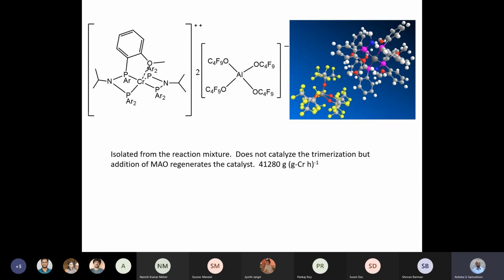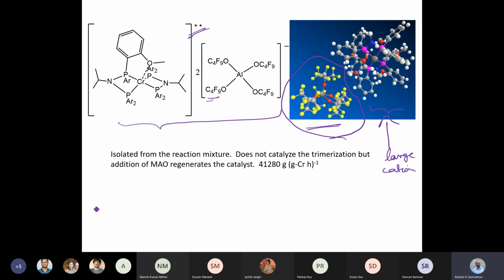This whole paper illustrates how important it is to study the catalysis carefully. What they have shown is that after the end of the reaction, they could isolate this catalyst. So here is this catalyst which has got a fluorinated alkoxy compound as an anion, as a counter anion. And this counter anion, like I told you in a previous slide, is separate from the cationic species. So this is a cationic species, this is the large species, large cation. And the anion is found separately, not interacting with the cationic species.